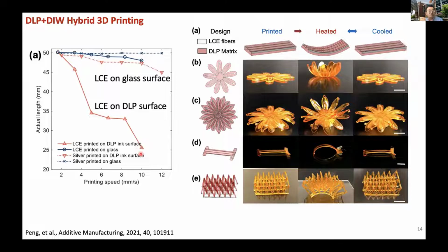So if you have oxygen present, it will not cure the ink. Instead, your radicals basically just combine with oxygen and become dead. That's what we call the oxygen inhibition effect. So in our top-down approach, the top layer is always exposed to the air, so you always have this oxygen there.